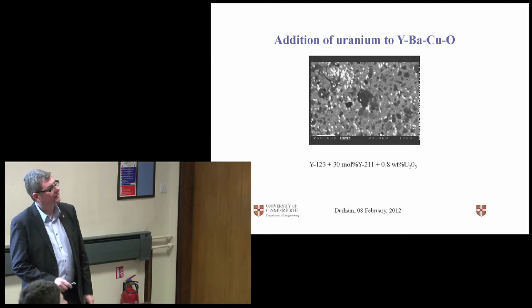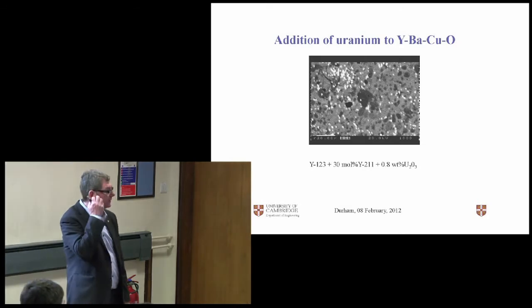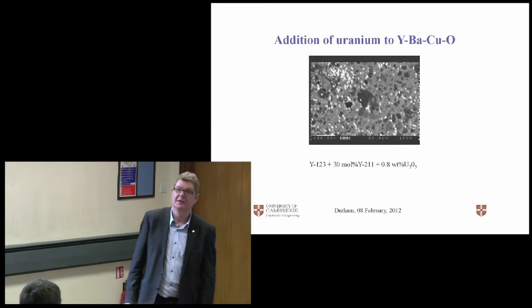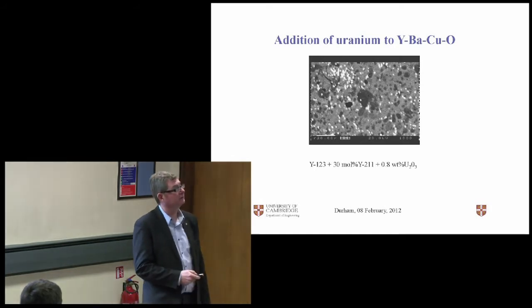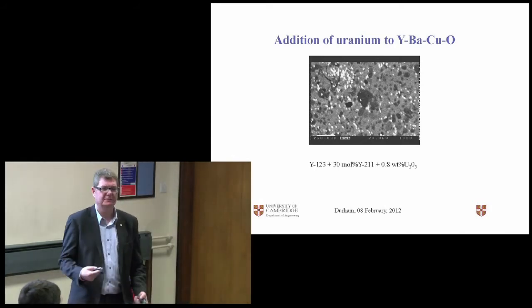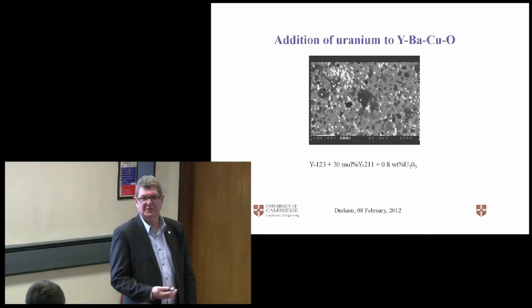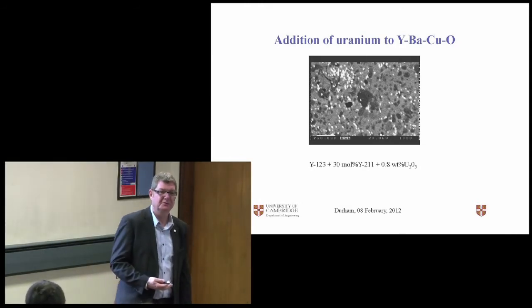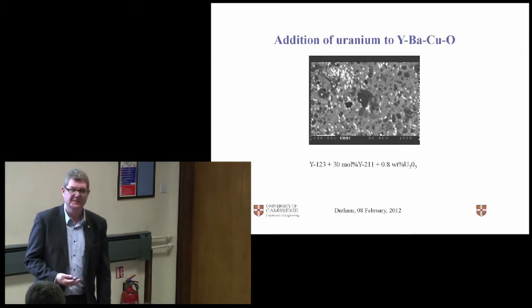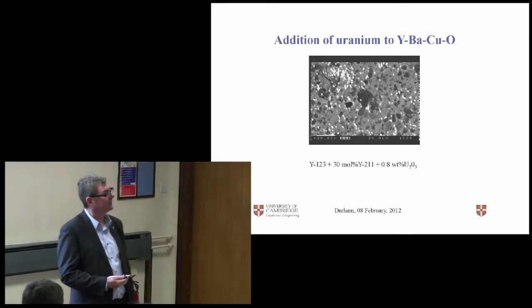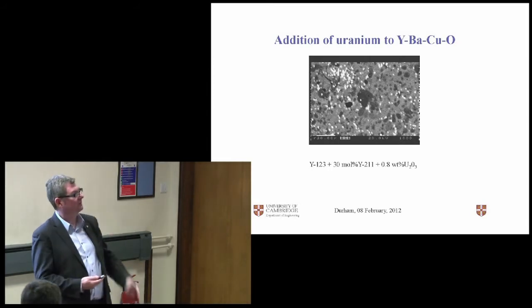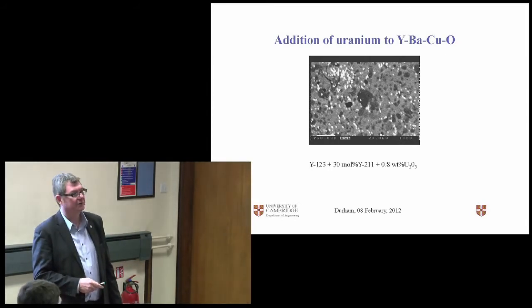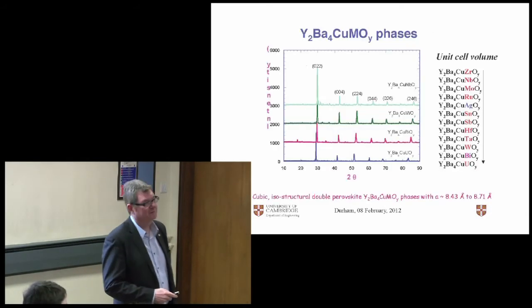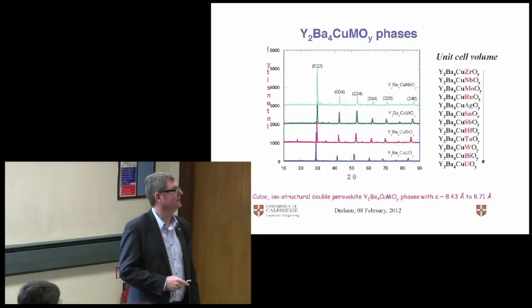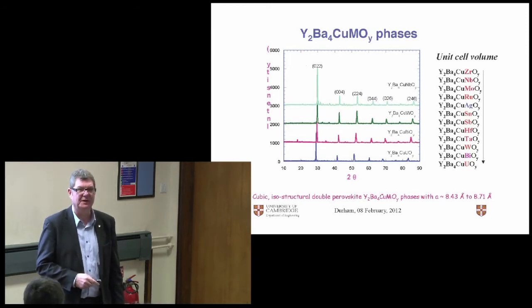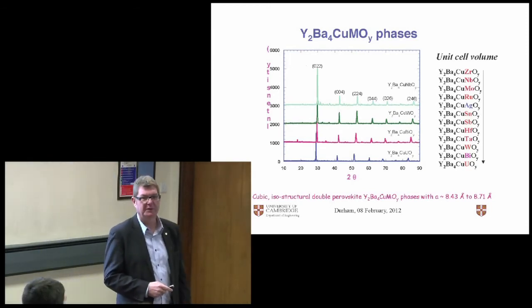It all started by adding uranium to YBCO. So there's a lab in the US at Houston, Roy Weinstein looks after that lab, and he reported, they're into kind of serious science, like putting lots of radioactive stuff in and zapping it with various things, and getting fairly spectacular effects, and having to wait 4 years before you can measure the sample because they're too hot. And he reported if you put fissile uranium in, it's all a bit scary, isn't it?